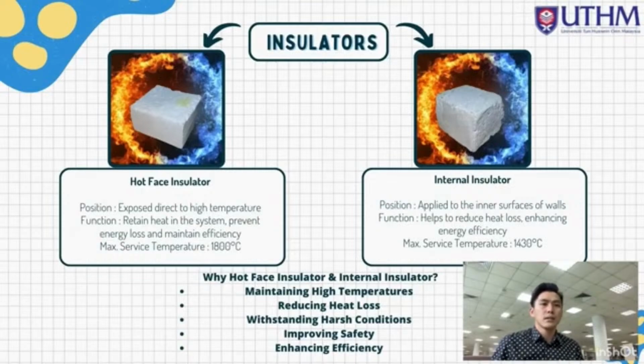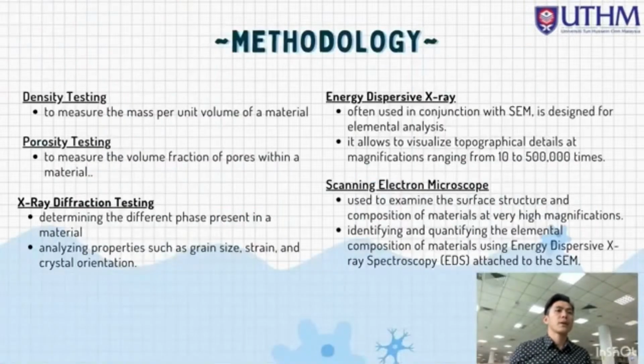And the second one is the internal insulator. Its position is applied to the inner surface of the wall inside the furnace. Its function is to help reduce heat loss and enhance energy efficiency. Its maximum service temperature can be achieved around 1430 degrees Celsius. So why were hot face insulator and internal insulator selected inside the secondary reformer furnace? Because both insulators can maintain high temperatures and reduce heat loss, withstand harsh conditions, improve safety, and also enhance the efficiency.